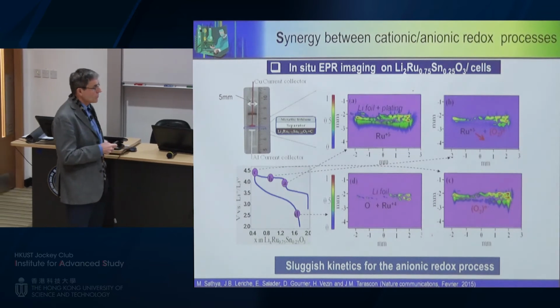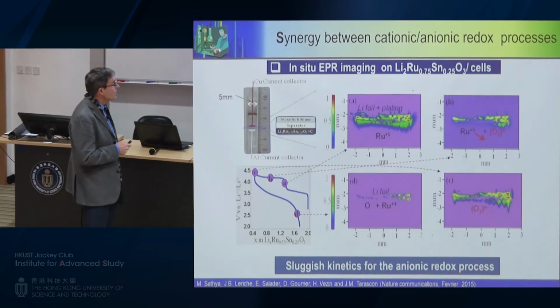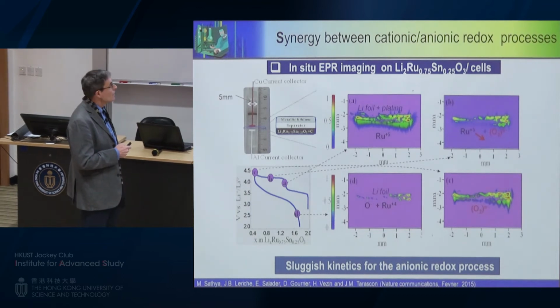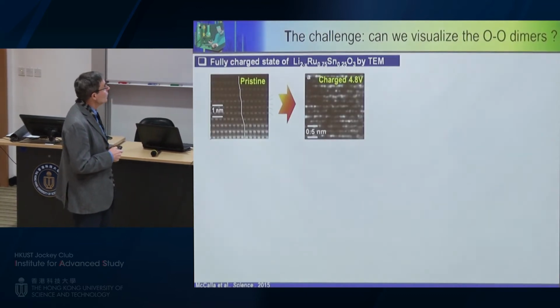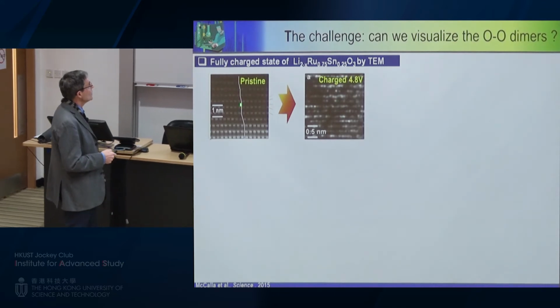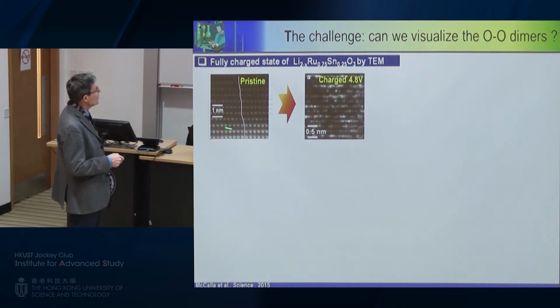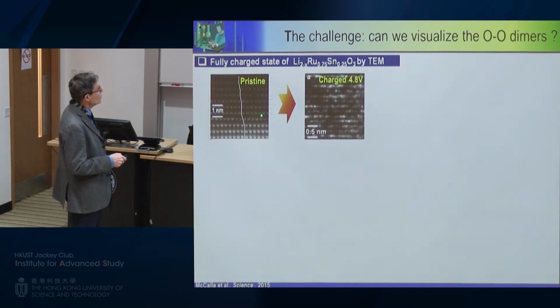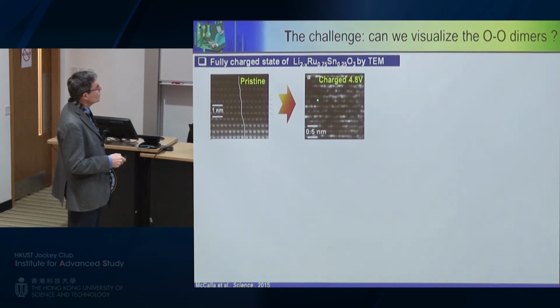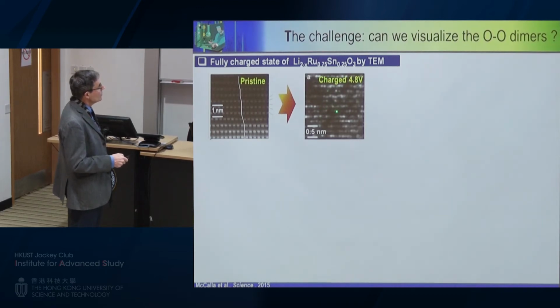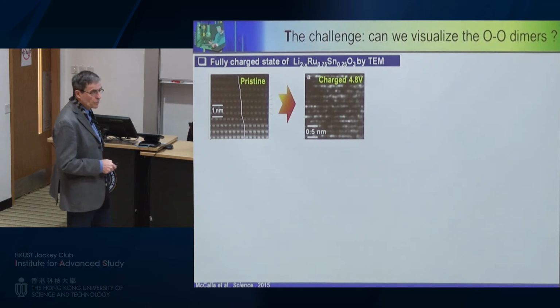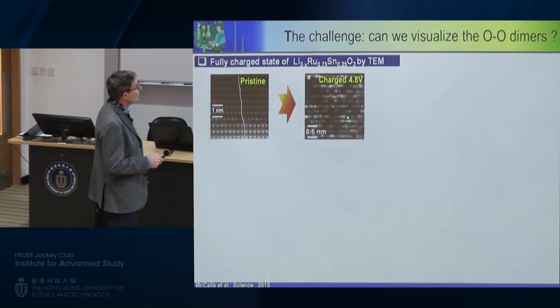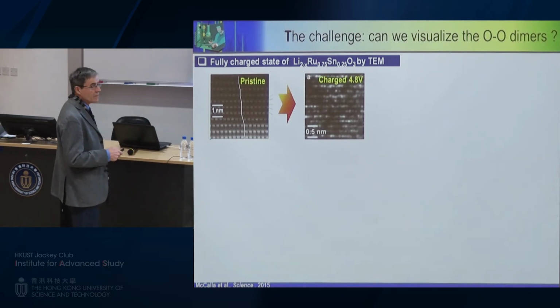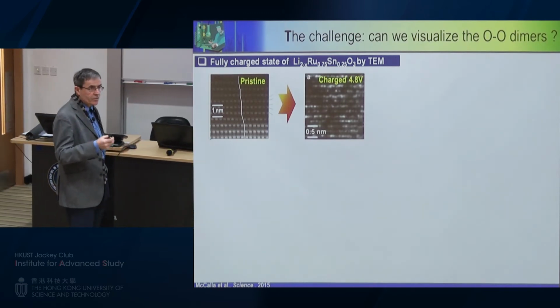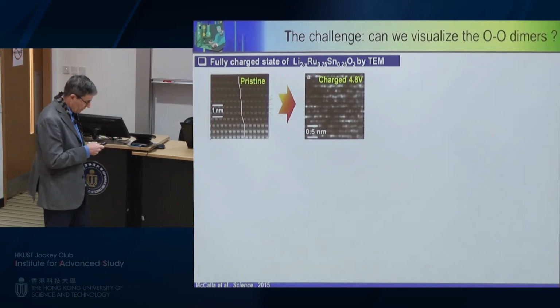So having determined this type of species, the next step was, in this case, can we observe this species? So we looked at it by microscopy, and what we found when we look at our compound here, you can see the nice structure, you can see nicely the layered compound with the two white spots associated to the heavy atoms within the metal layers. And then when you go to very high voltages, charge, you can see there is a huge amount of disorder with cations moving from the metal plane to the van der Waals gap and so on. So there is no way that you can observe some structural feature or some kind of distance in these materials.